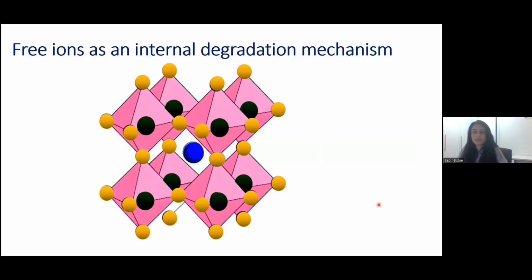The conduction in the perovskite is ionic-electronic conduction. The ions, which detached from the crystal, take part in the currents and change the charge distribution in the device. They also can affect the electrical measurements and cause hysteresis, but worst, they cause internal deterioration of the device. So we found it important to explore them.